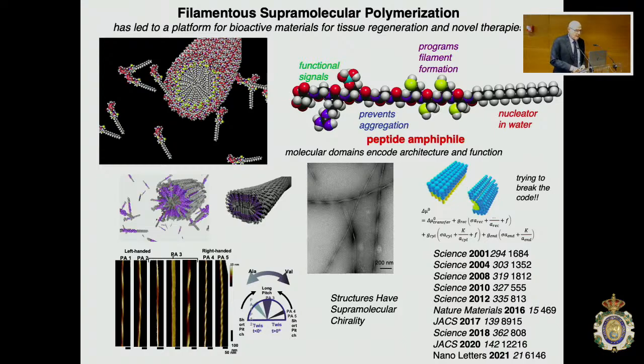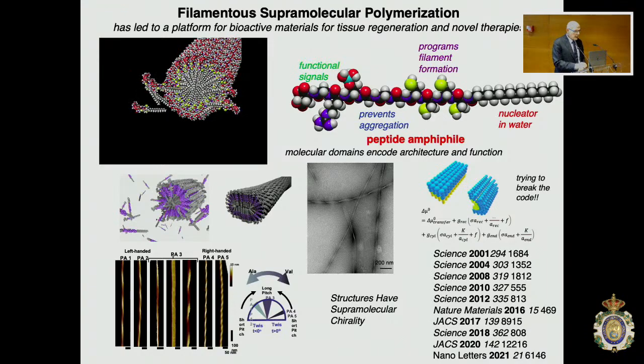Another example are these systems which I have spent now 20 years studying, and these are the materials that we called peptide amphiphile supramolecular materials. They are fibers that are formed by specific molecules that, as you see on the slide, self-assemble in water to create a fiber. And that fiber sometimes is cylindrical, or as you see down here at the bottom, has the cross-section of a football stadium, okay? Or sometimes it twists, as you see in the micrograph in the middle of the slide.